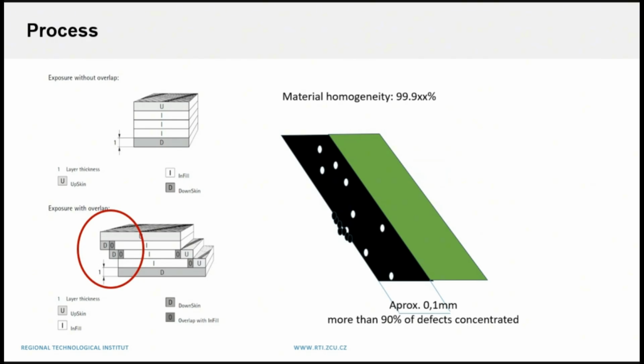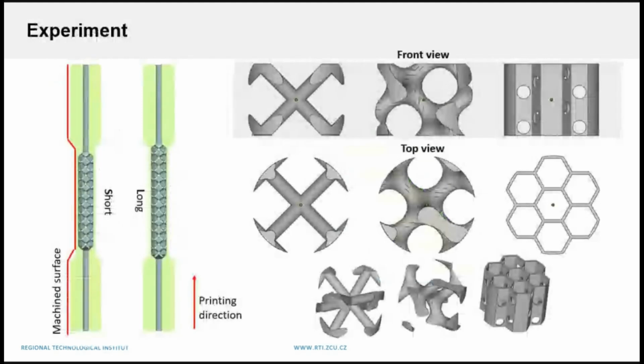So for the experiment, in this case of lattice structure, we prepared standard samples, but into the body, into the shell, we implemented 2 or 3 different lattice structures, BCC and gyroid structures. And what we did, the internal hole, we finished in this area. We should call it a short system. And the second, we ended the internal hole a little farther from this area, only a few millimeters.